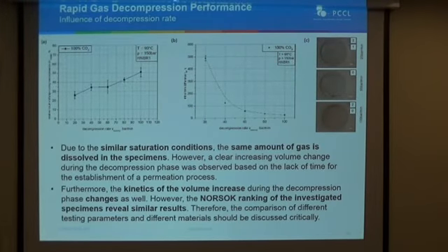When we also look at the results of the NORSOK ranking, for the NORSOK ranking we did not see any differences, so we cannot easily correlate these volume changes to the NORSOK ranking of the material.